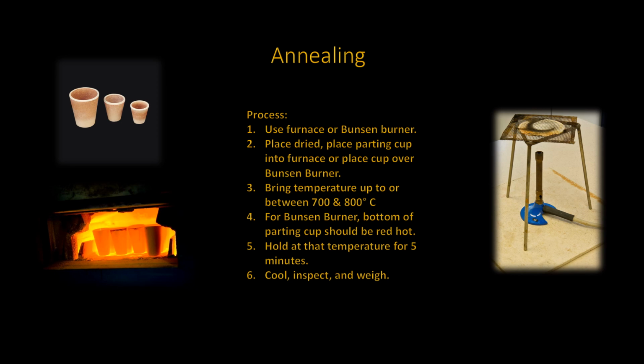A lot of videos will present annealing using a torch. This is not really recommended. The pressure produced by the torch, which is directed directly onto the bead, may cause airborne particles to be impregnated into the bead, thereby contaminating it. If not using a furnace, a Bunsen burner is a safer method for the annealing of those parted beads.